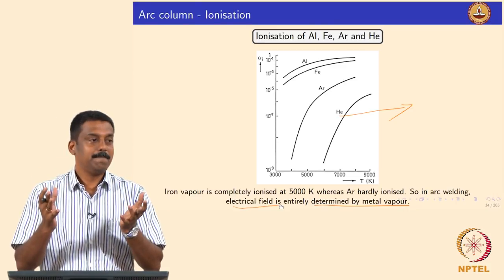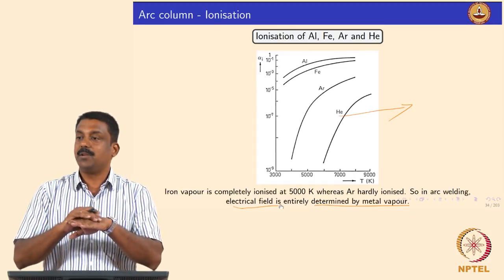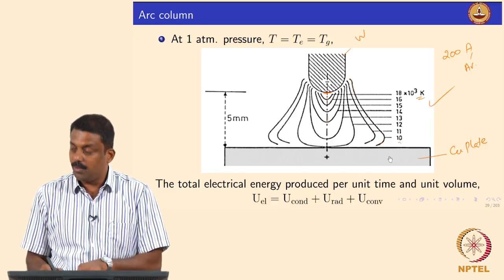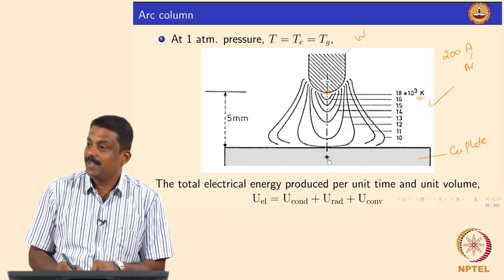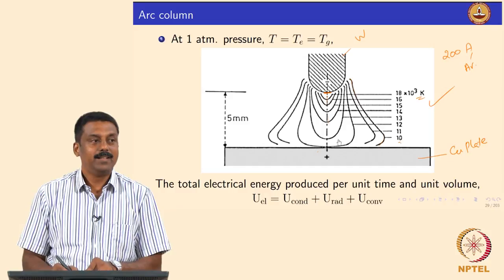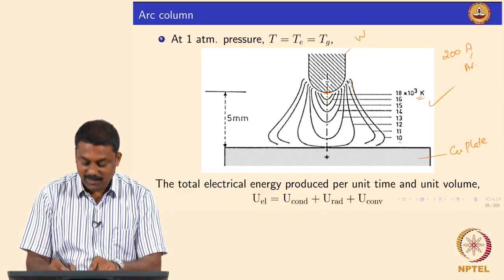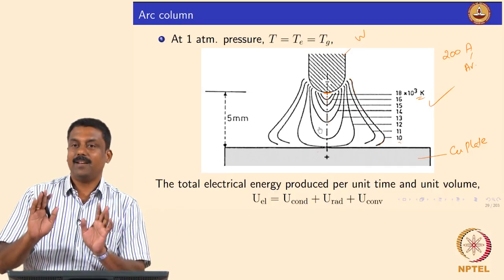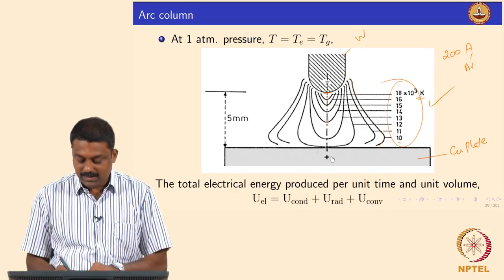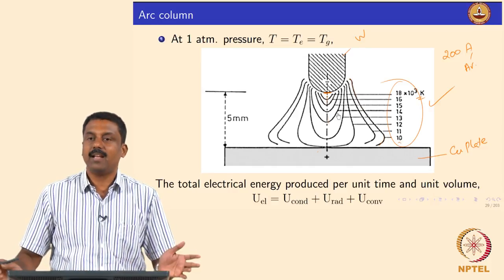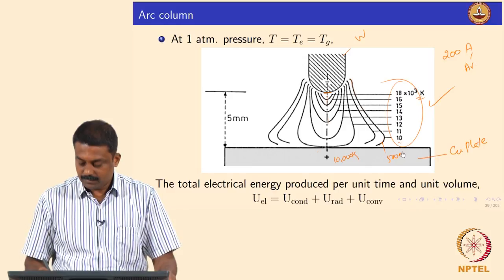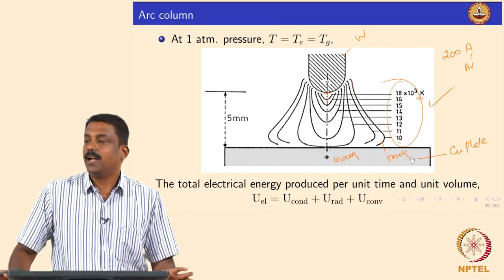In the argon case, when you have a shielding gas and the anode is not molten — the figure I showed uses a water-cooled copper plate, meaning copper is not vaporizing — so the arc here is fully created by the ionization of argon. If you are not melting and vaporizing the anode, you can know exactly the temperature of the arc due to argon alone; that is how the temperatures are much higher.